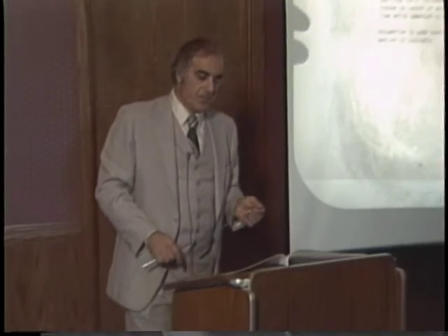Next slide, please. Now, you've seen a lot of relative permeability columns up here. The technique that we chose to use to evaluate materials as far as permeability went is called a swelling ratio technique. The way we do that is we cut a strip of the liner material, we put it in the migrant of choice, and we follow the change in length of that material with time. We assume that the change is isotropic, that the material expands in all directions at an equal rate, and simply ratio the cube of the length of the material relative to what it was initially, and we come up with a swelling ratio.